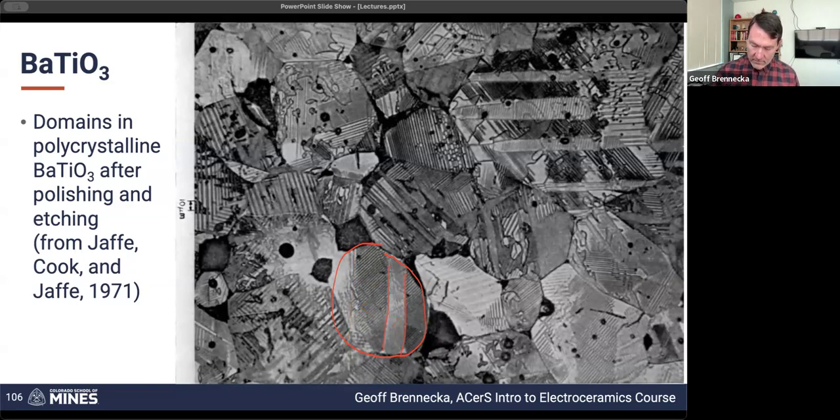So this one, the herringbone is that way. So we've got 180 degree domain walls that are charge compensating. And then this one is 90 degrees to that one. But then we also have positive and negative 180 degree domain walls within that. And so you combine all of these and you end up with a really messy looking overall picture where each individual grain is randomly oriented.